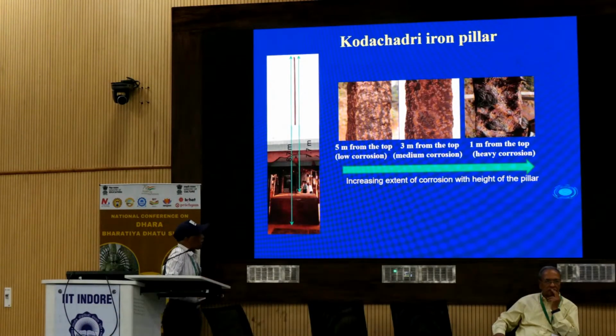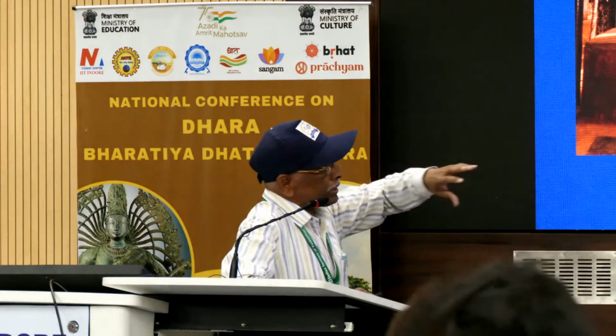And this is the Kodachadri iron pillar. I think the information has already been given with respect to this pillar about dimensions, etc. This cross section is relatively small, and we have taken some studies here also from different portions. And then if you see, the corrosion rate varies from bottom to top. In the top region, the corrosion is very high, whereas as you come down, the corrosion rate is low. Another point is that this pillar has a square cross section, and the side which is exposed to the Arabian Sea, the west side, has the highest corrosion, whereas if you see the face on the eastern side, there is almost very little corrosion.